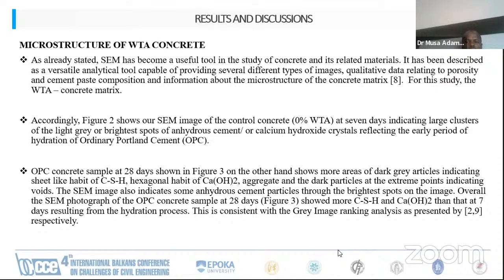So for this study, the WTA concrete matrix, according to figure 2, which is shown in the next slide, our SEM image of the control at 7 days indicates large clusters of light gray or brightest spots of anhydrous cement or calcium hydroxide crystals, reflecting the early period of hydration of Portland cement.